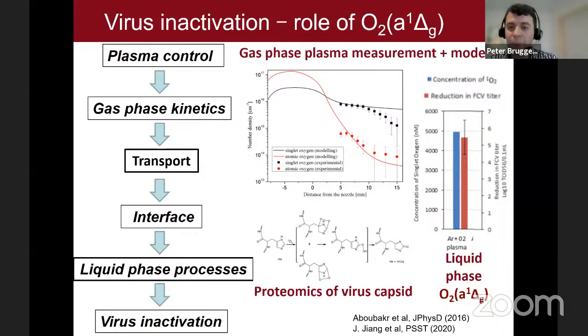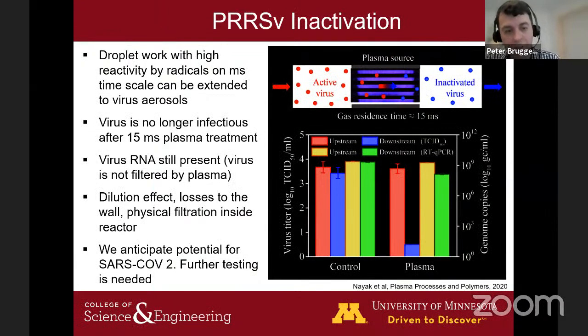Now, I talked about transport limitations, and I just wanted to show this because people are typically very interested in that in view of the pandemic. So typically it took us about a minute to inactivate virus on the surface, which is a bit long. And particularly in the pandemic situation, aerosolized viruses are potentially a bigger problem, certainly for certain viruses. Now, that work was actually done before the pandemic, but motivated by the transfer of animal virus. But if you want to do this in air handling systems, you need to be able to inactivate within like 10 milliseconds, okay? So this is about 1,000 times faster than we did on surface.